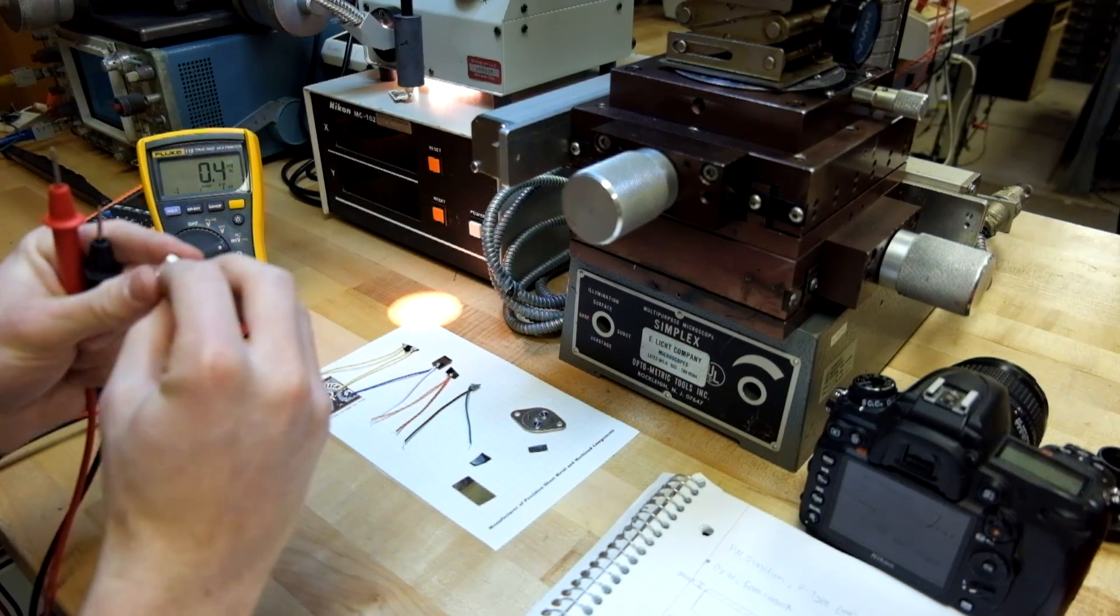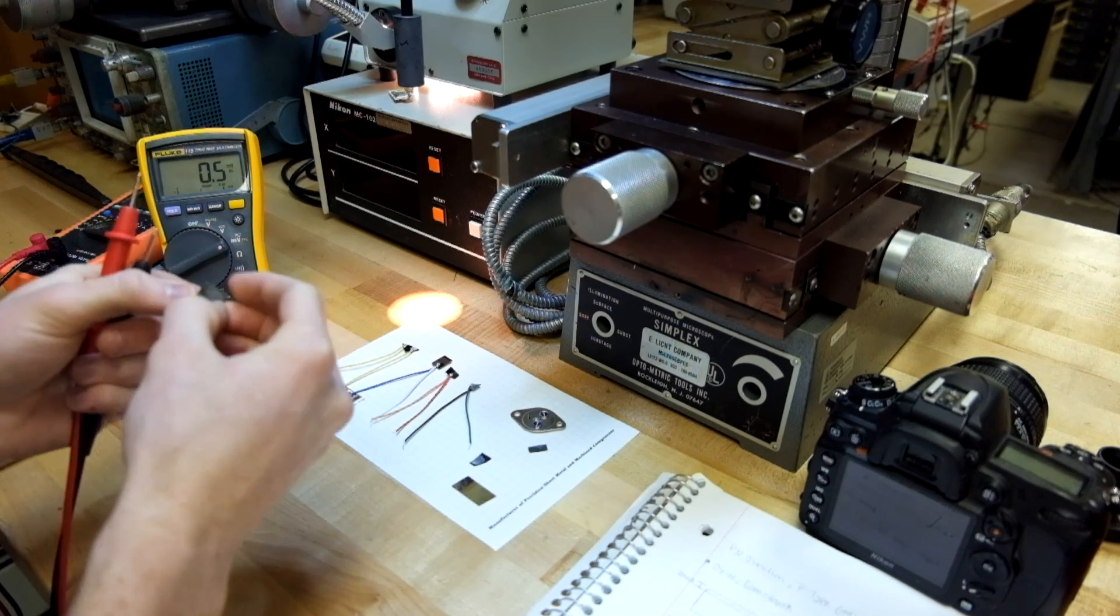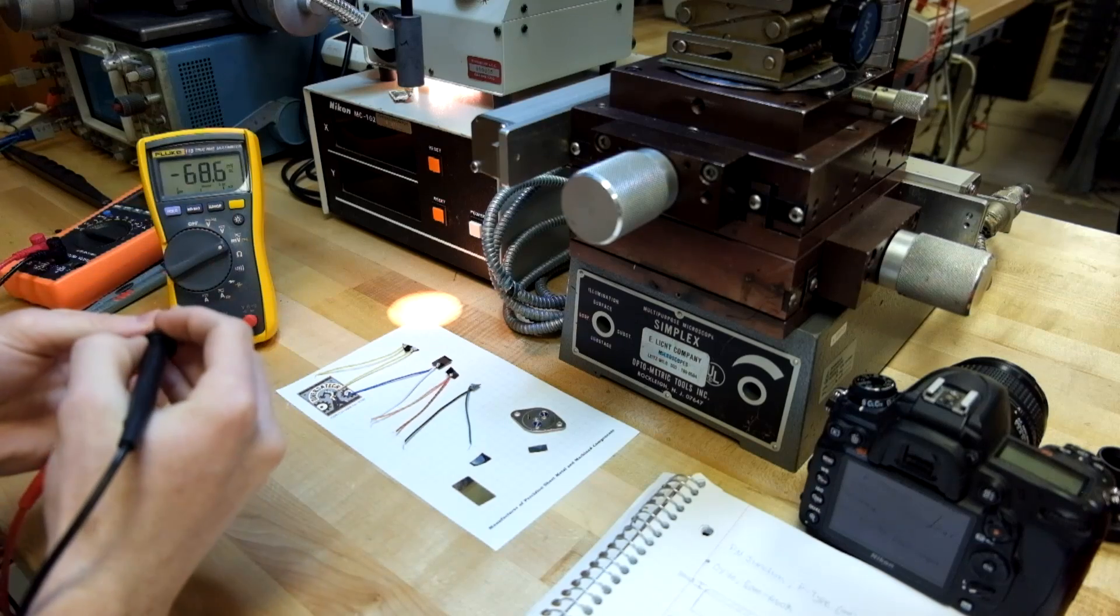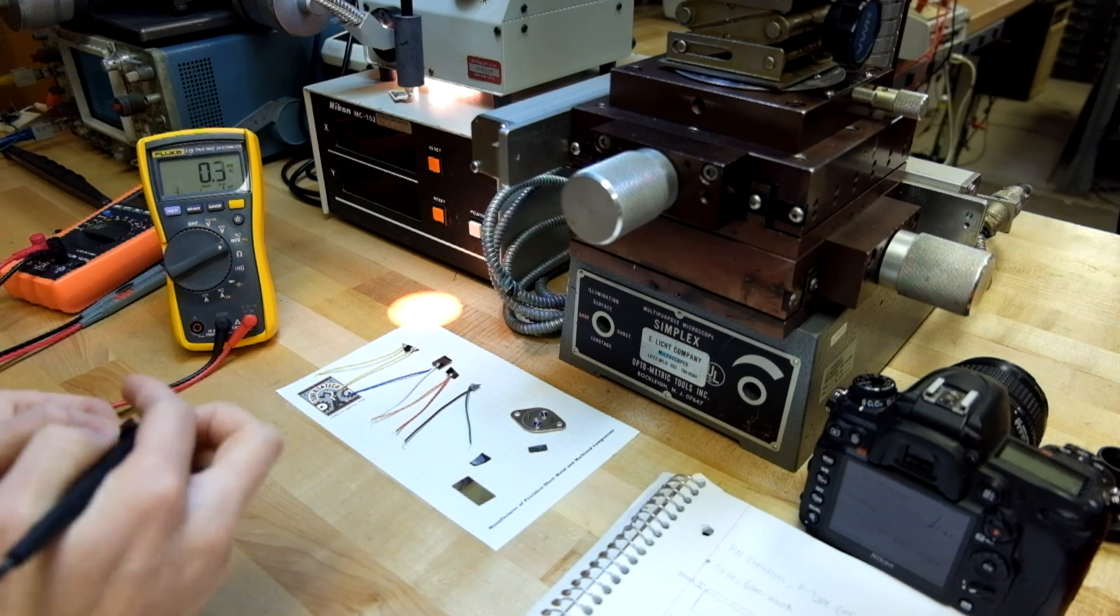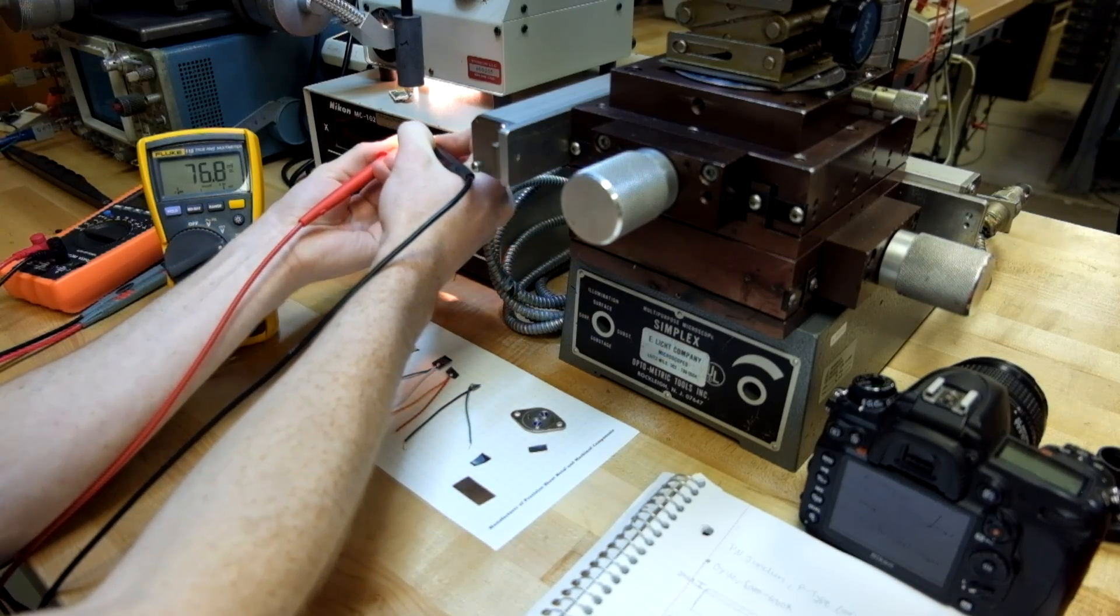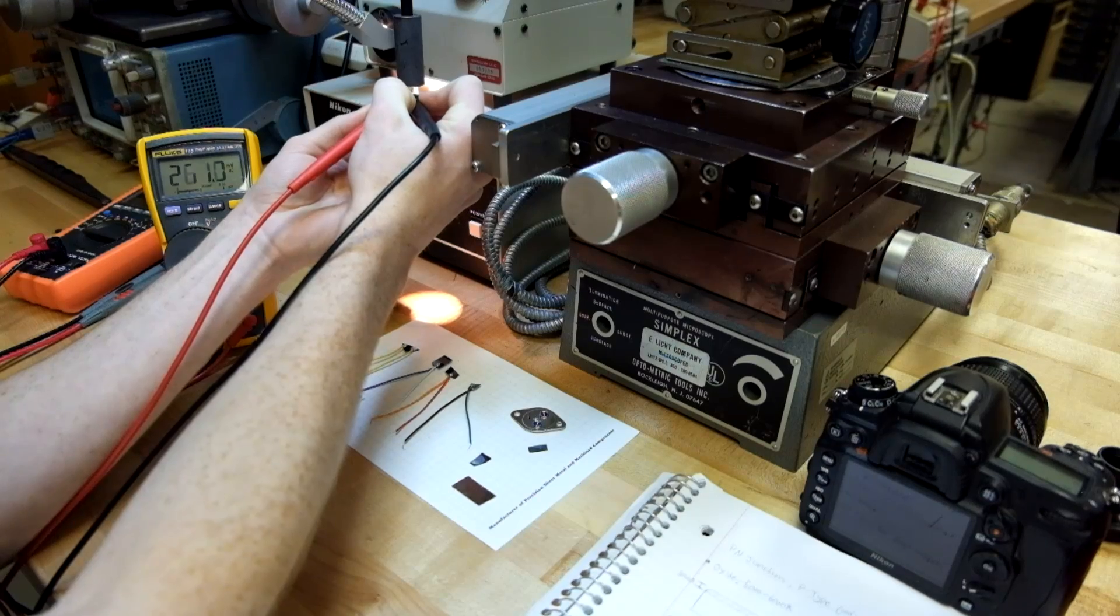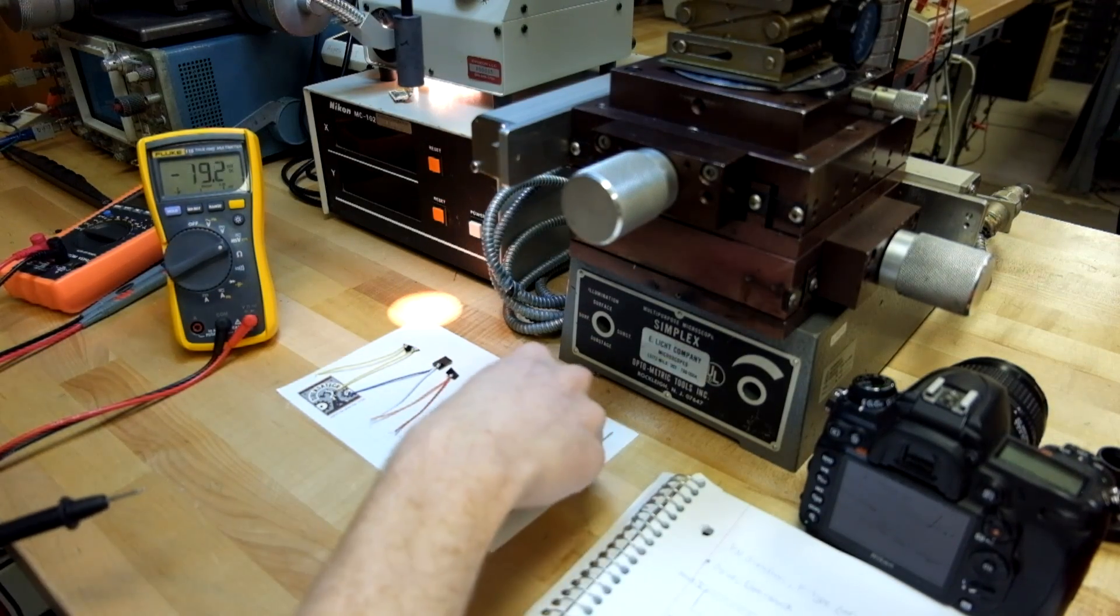And the last thing I'll show you is that yellow-colored Coca-Cola doped wafer. The front of it, the yellow is from thin-film interference of the silicon dioxide. The back of it actually has some caramelized sugar on it, which is funny. And I kind of scraped away a nice portion of it so I can make a connection with the backside of the p-type wafer. Again, almost a quarter of a volt there.